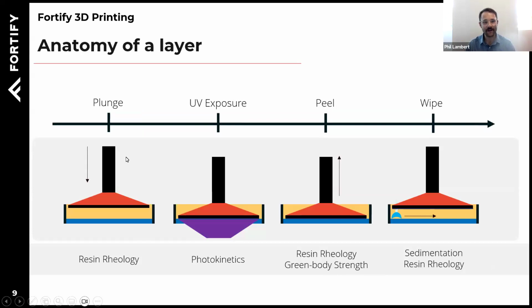Starting on the left, our build plate plunges into our vat of photopolymer resin, and that build plate plunges until it's just one layer high above our glass substrate here. And then we illuminate with our digital projector to create a cross-section of our image in our photo-curable resin. So we can see just a little sliver of our resin there. That's one layer's worth of resin that gets cross-linked in a shape.